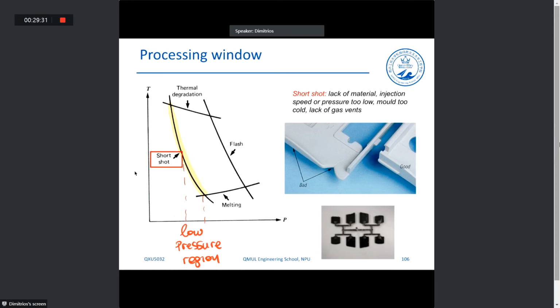That can be an effect of the speed or the pressure of the injection molding being too low, or the mold is too cold before the polymer comes in the mold. And in this case, you can see that we don't have completely, fully developed material. These are essentially lack of material. So short shot is because we don't have enough material injected into the mold, we have low injection speed, okay, but the speed essentially is related to the pressure, which is the most important. So the pressure is too low, so we didn't inject enough polymer within the mold, or the mold was too cold, so it didn't accept all the material that it could.